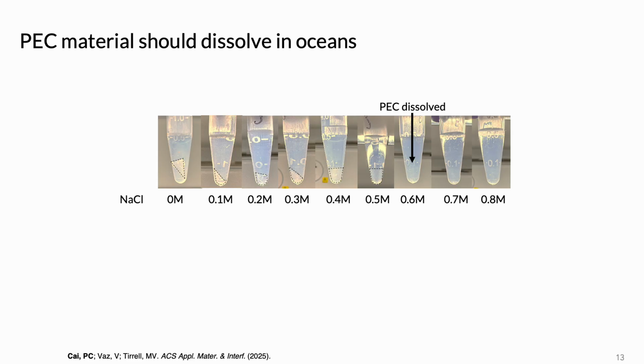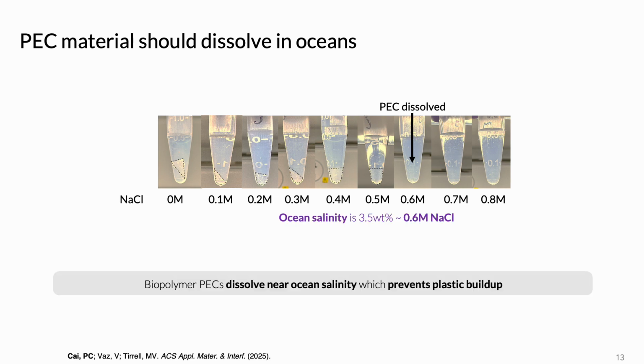One thing that really struck me years ago was the sheer size of these large floating islands of plastic in our oceans, the most polluted one being the Great Pacific Garbage Patch that's twice the size of Texas. How do we avoid that? Well, it turns out this biopolymer PEC currently can dissolve at around ocean salinity. If we convert ocean salinity to sodium chloride concentration, which is what I'm using here, it's around 0.6 molar sodium chloride, and at that concentration, we find that the PEC fully dissolves into the salt solution.